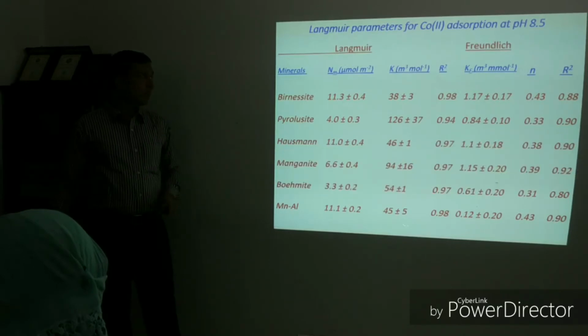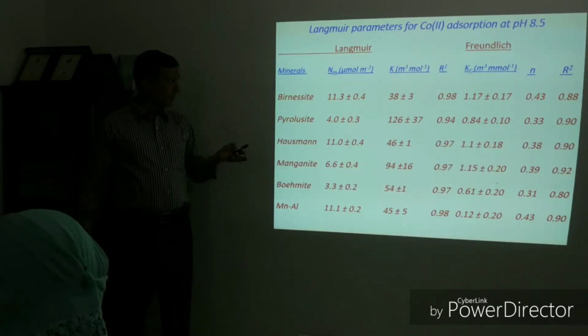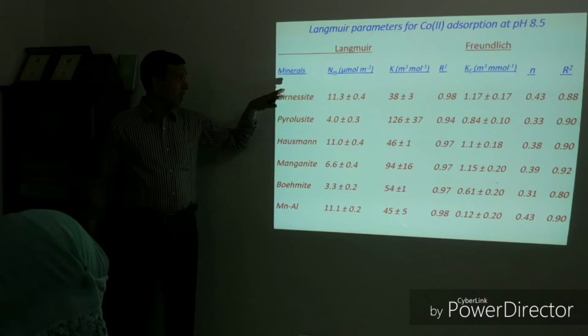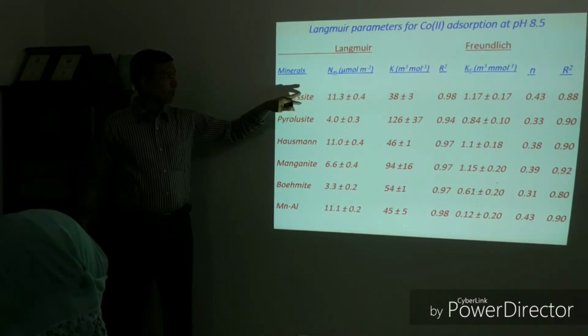These are the results for a typical cobalt adsorption at pH 8.5, and from this table we see that birnessite exhibited maximum adsorption of cobalt, and boehmite exhibited the lowest adsorption of cobalt under our experimental conditions.